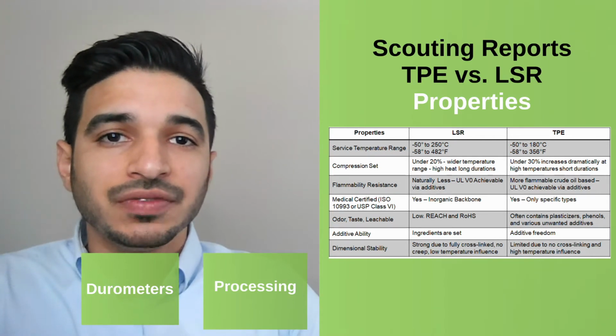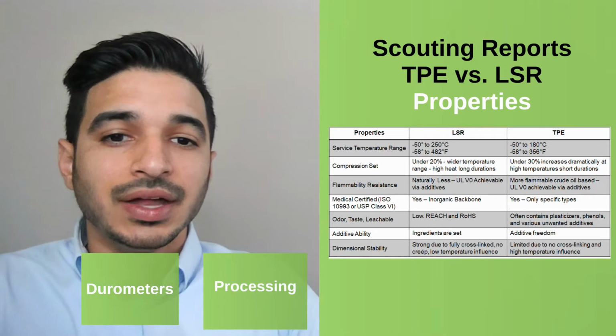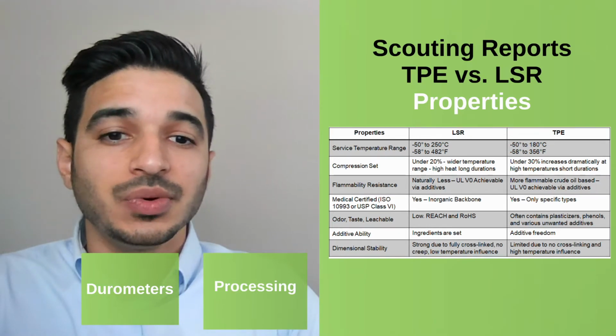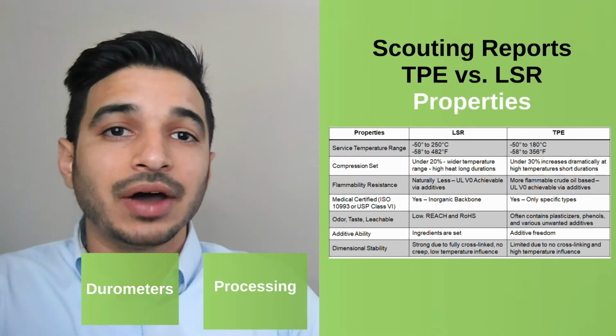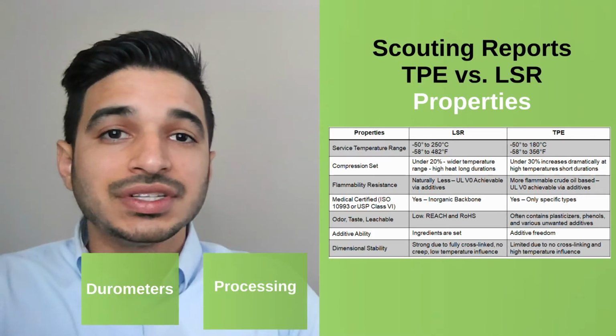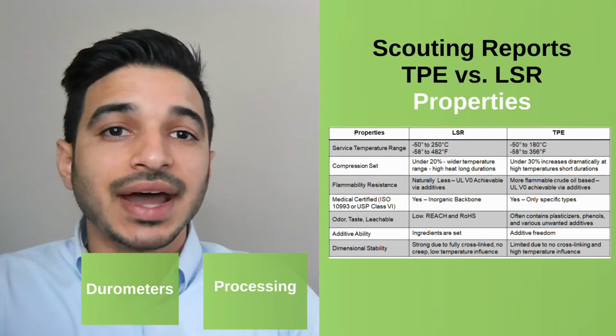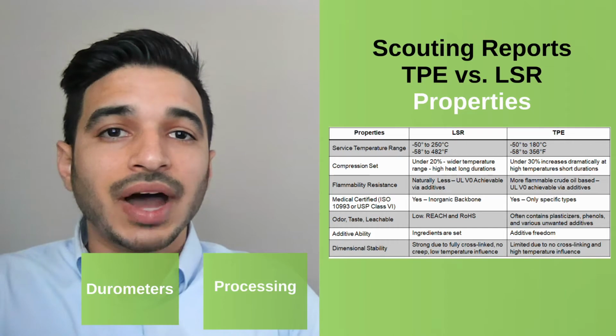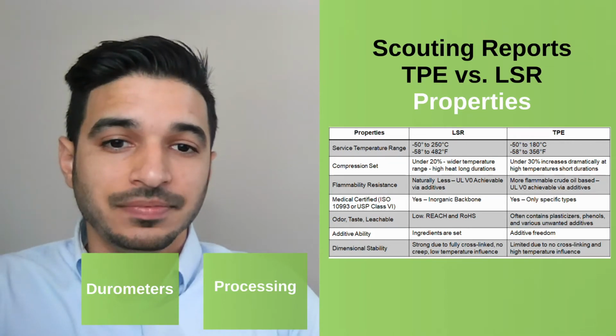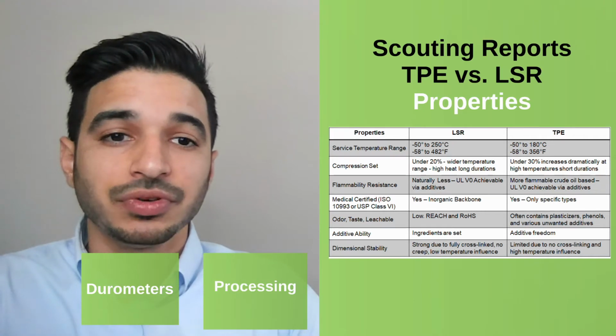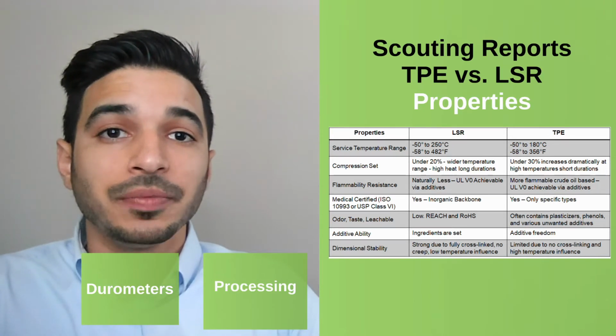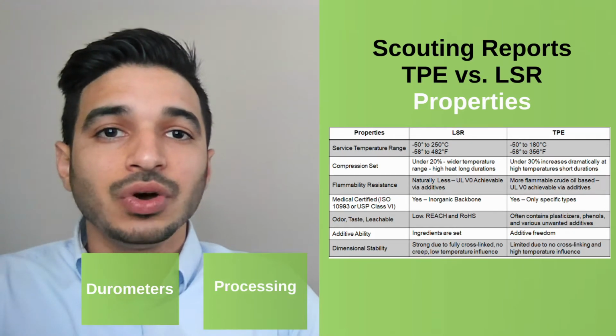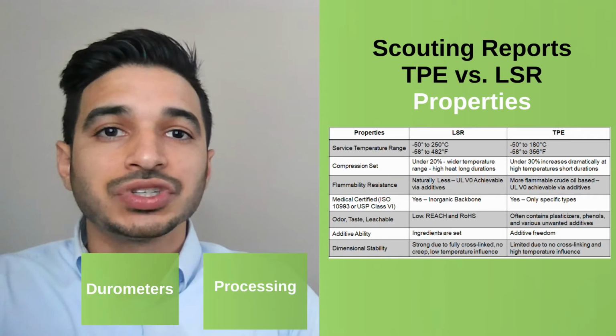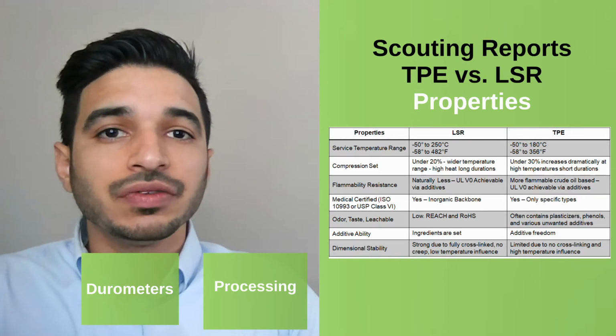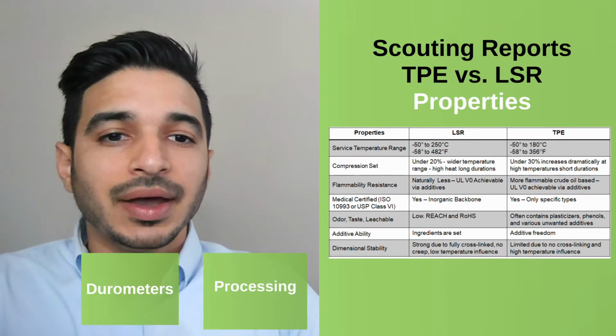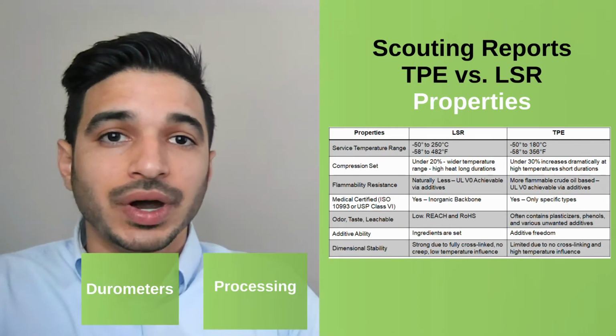When it comes to the medical certifications needed for the medical industry, these two, ISO 10993 and USP Class 6, testing for biocompatibility and cytotoxicity, LSR is naturally going to pass these every single time because it has an inorganic backbone, whereas TPE will have a limited selection to pass those requirements. When it comes to odor, taste, and leachables, LSR has relatively very low. The only thing it has is these low molecular weight siloxane chains, which are often also called volatiles, and they're driven out via a post-curing process. And also LSR can achieve REACH and RoHS quite easily.